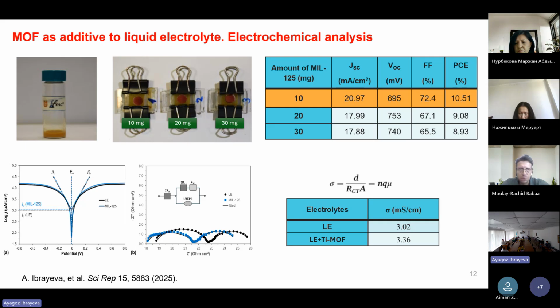Then for the electrochemical analysis, we provided Tafel and symmetric cell analysis. By the exchange current density, we can say that in the case of quasi-solid electrolyte, electron flow was faster at the counter electrode and electrolyte interface. In the symmetric cell analysis, the lower charge transfer resistance confirmed this, and we obtained better results. Also, we calculated ionic conductivity, and it was higher, 3.36, in the case of quasi-solid electrolyte.